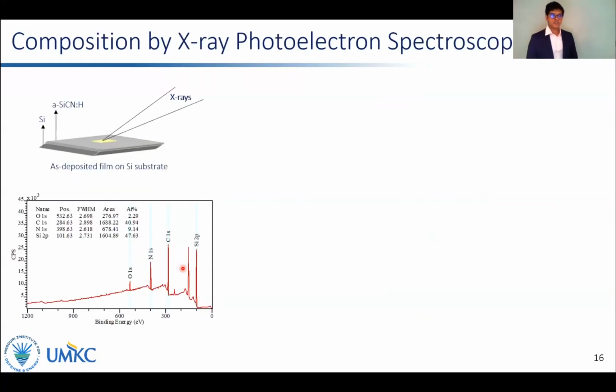We used XPS to estimate the elemental composition. XPS relies on measuring the binding energies of the core electrons of atoms. The binding energies of the electrons are specific to atoms, which makes XPS a robust technique to quantitatively estimate the elemental composition. This is an example XPS wide scan spectrum of one of the samples.